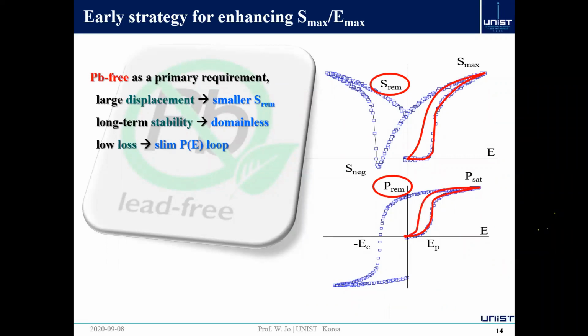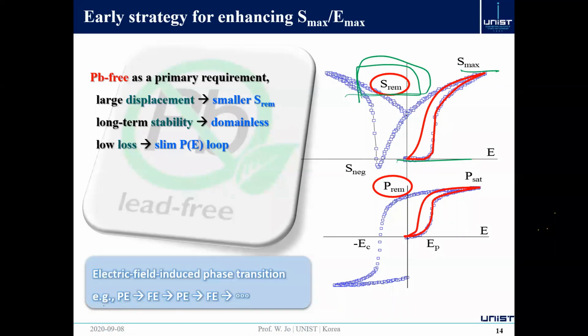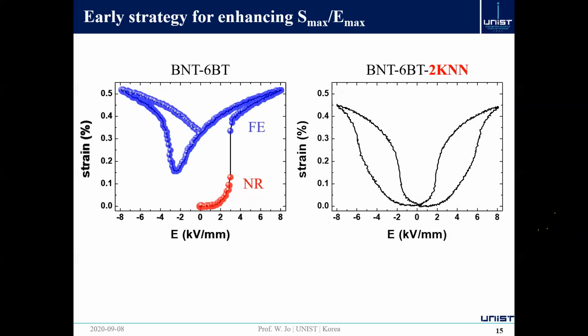So our early strategy, when I was working in Darmstadt, was focusing on this high strain material. And the idea was really simple. Simply removing remnant strain will give us really high strain. Removing remnant strain could be done by introducing a paraelectric phase at zero field, which is quite possible in relaxor materials, or you probably can utilize the phase transformation. And this repeating phase transformation will give you a really high strain. So this is our early achievement, and how this large strain material is different from the typical ferroelectric materials.